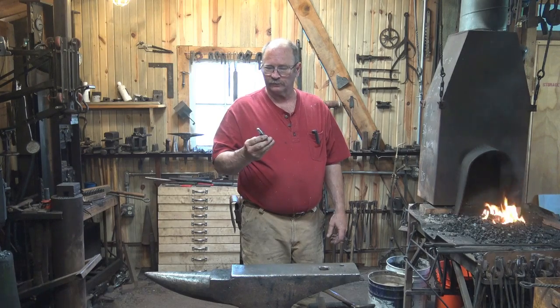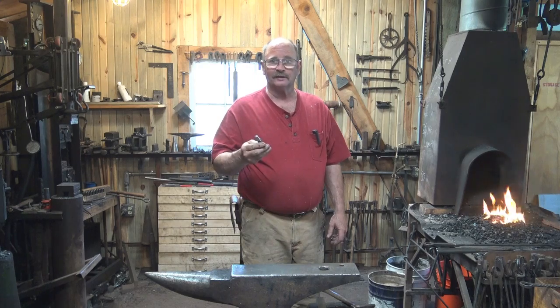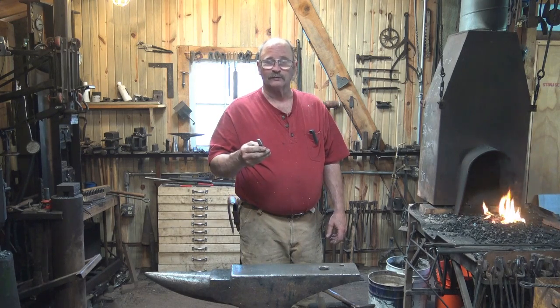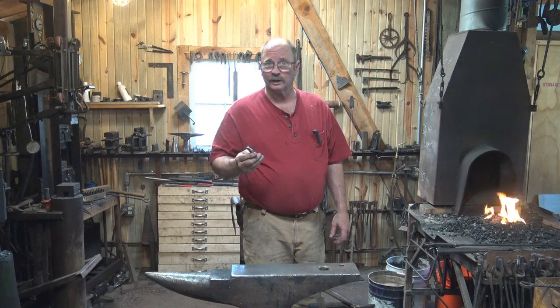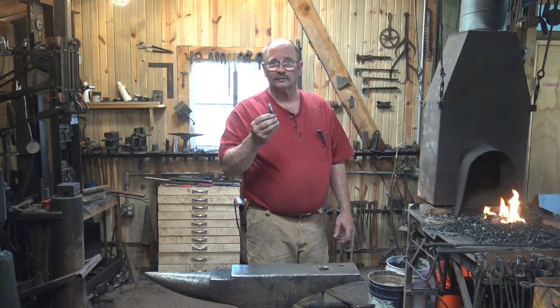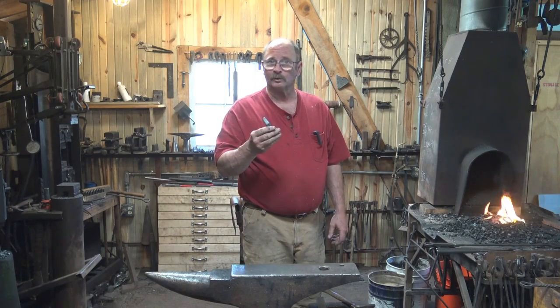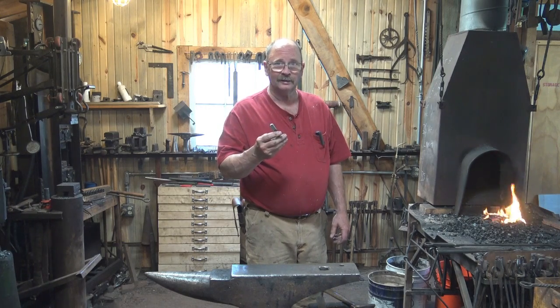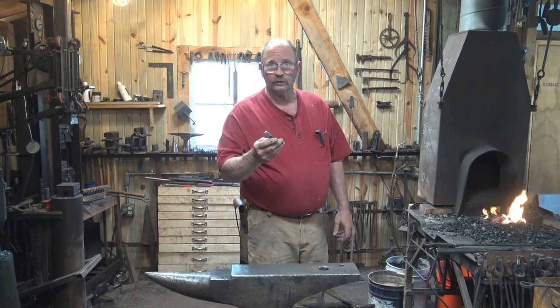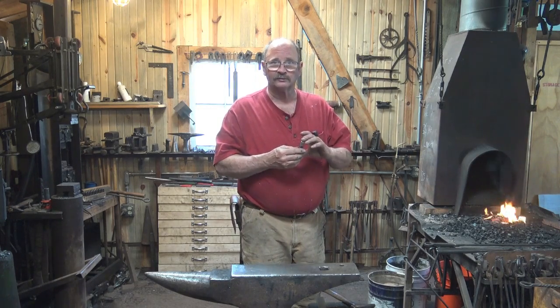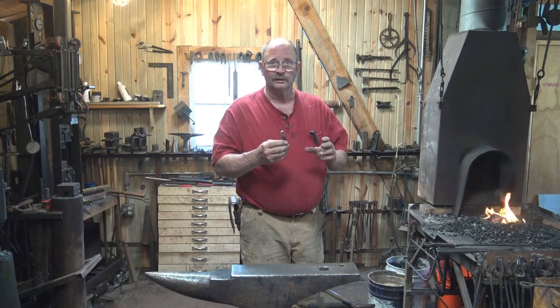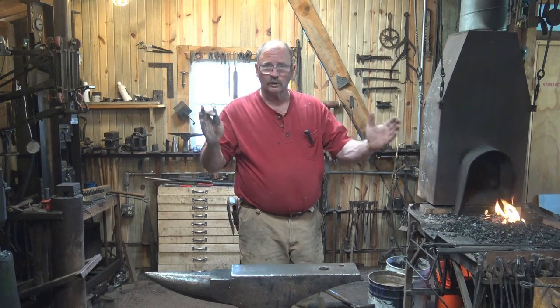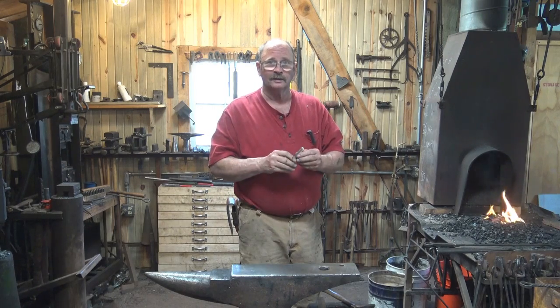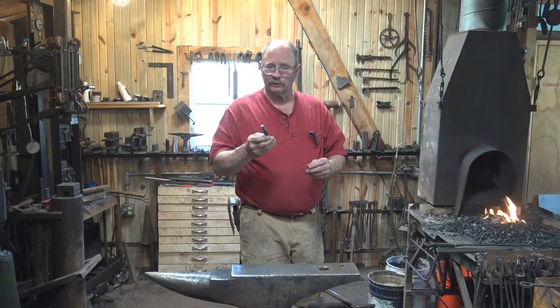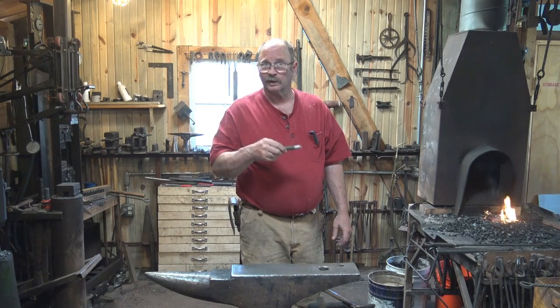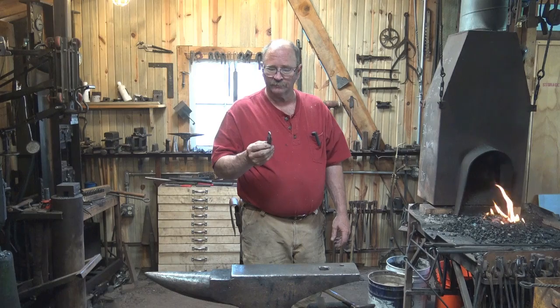Heat treat process on this is no different than everything else we've ever heat treated. It's just a matter of bringing it up to the proper temperature and quenching it in the proper medium. In this case, the proper temperature is about 1500 degrees, and we're going to guess that by eye today. And the quench medium is oil, and that's based on tests I've done on this same section of coil spring. You get a section of coil spring, you do the test once, you know the whole spring is going to heat treat the same way, so I don't have to do it over and over again. So I already know how this is going to behave. Next time I get a coil spring, I'll have to do something different.